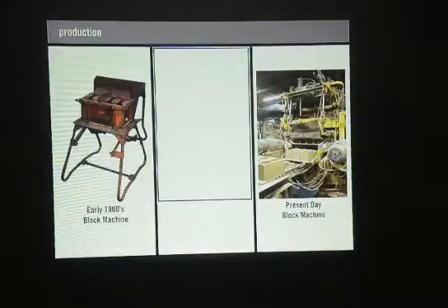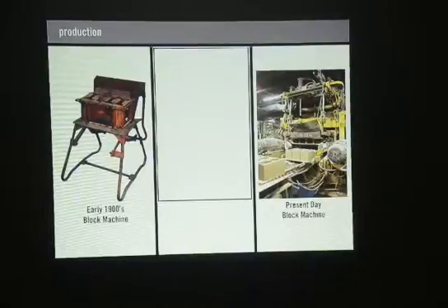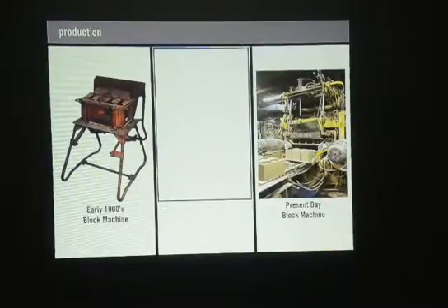It was actually made by hand as far as the mixing of the water and the powder and the aggregates. They mixed it for about 2 minutes. Then they put it into the hopper area and they turned the crank. It took about 12 seconds to produce 1 block.